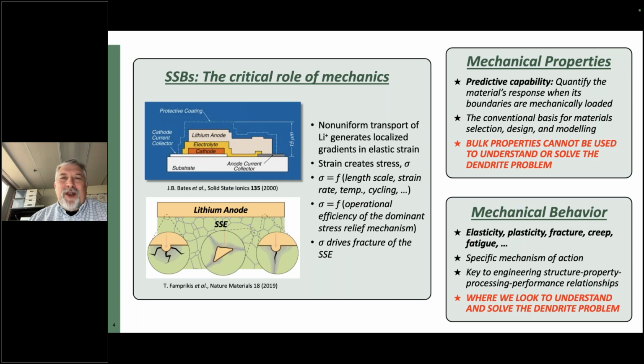And I'm going to let the cat out of the bag here a little bit, because one of the really key pieces of the story here today, at least the story for me, one of the things I'd like you to remember is that we can't use the mechanical properties of bulk lithium metal in order to engineer mechanically stable interfaces, or as the slide points out here, to solve what Sergey pointed out about solving the dendrite problem. Yeah. So the reason for that is that the bulk properties of lithium basically don't reflect what's going on at these relatively small length scales here within these morphological defects, okay?